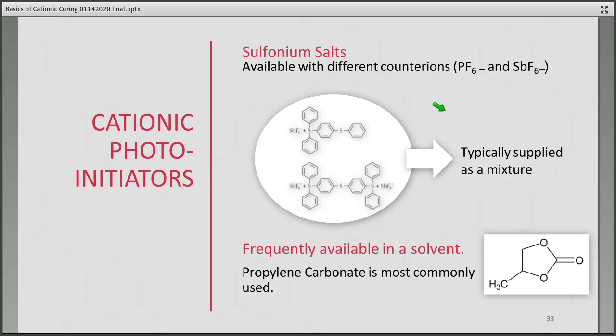When you purchase these or obtain these from a commercial supplier, they're typically supplied as a mixture of these two components. And here's the antimonate system. It works, I think, the same for the phosphate. You have the sort of mono and the di system. That doesn't affect your activity or the ability to use these materials. They work perfectly well as a mixture. So you'll find them as a mixture.